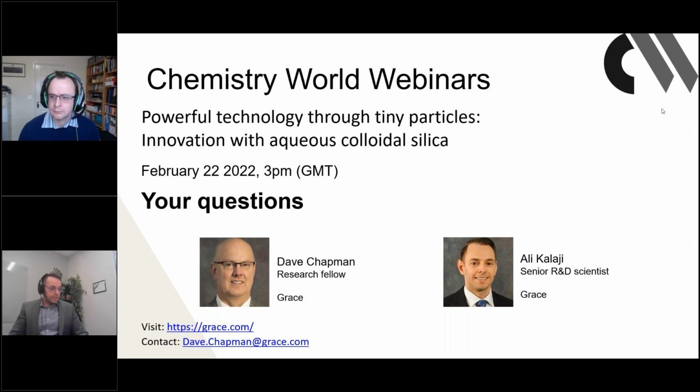Another very important property is the pH range that you expect the colloidal silica will be experiencing in your system. Most of the colloidal silicas are stable at a high pH, alkaline, but we also have some grades that are stable at the low pH range. And finally, the charge of the particles. If you want a particle to be attracted to negatively charged surfaces, then you would choose a cationic particle. So those are the particle size ranges, the pH that you expect, and again, the charge on the surfaces. Great, that's a really comprehensive answer.